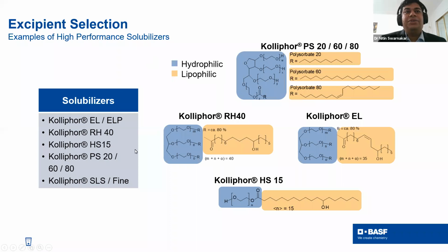Now coming to the excipient side, we have very good solubilizers: Kolliphor RH40, Kolliphor polysorbate 20, 60, 80. We have Kolliphor EL and Kolliphor HS15. These are very good materials to solubilize the API, because sometimes the API goes inside the matrix, interacts with the polymer, and doesn't come out. If you have a solubilizer, it will come out. Or sometimes you have a drug which generally crystallizes out. You can use these solubilizers at that time, because they have long chains which generally inhibit crystallization.